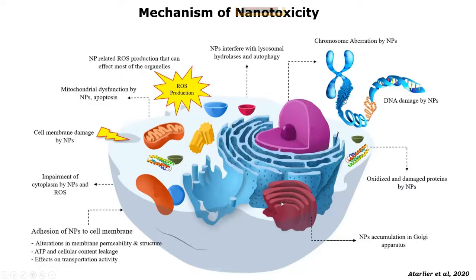Then your nanoparticles are also susceptible to degradation in this kind of physiological environment. So they are either in the late endosomes or the lysosomes after endocytic uptake. Now, when they face enzymes like cathepsin at a pH of 5.6 in the late endosomes or 4.5 in case of lysosomes, this degradation or dissolution of your nanoparticles can also result in the leaching of free ions or an increase in reactive surface groups, which happens in cases like quantum dots. So there are certain key features, such as the concentration of a nanoparticle, that need a very prominent understanding from the very beginning of designing your nano vehicle.